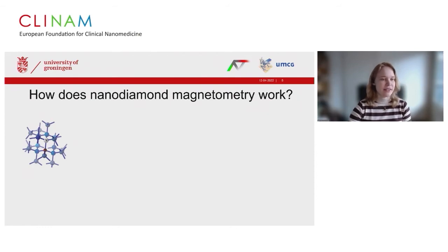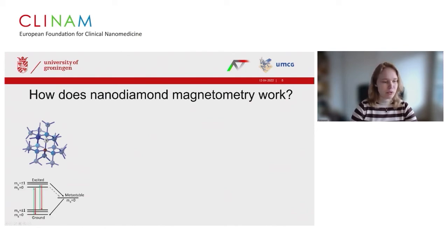As I said, the nanodiamonds are fluorescent due to their defects. They're called nitrogen vacancy centers. In this case, one atom of carbon is replaced by nitrogen, and the position next to it is vacant. This whole thing is fluorescent. What's more important, its energy states are arranged in such a way that its fluorescence can be different in its intensity. We can use this to our advantage.